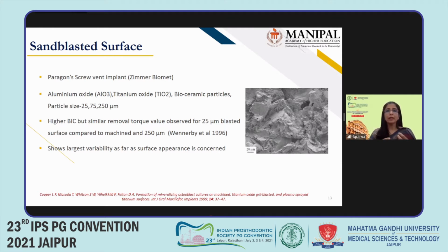So what does it do? It typically leaves a crater. That means a portion of the implant is removed in that area. It's leaving a small crater. So the surface roughness that you get by sandblasting is dependent on a number of factors. It depends on the material that the implant is made up of, in this case, titanium. The size of the gritting agent, and not just the size, even the shape of the particles, the density of these particles, as well as the speed at which these particles hit the implant.